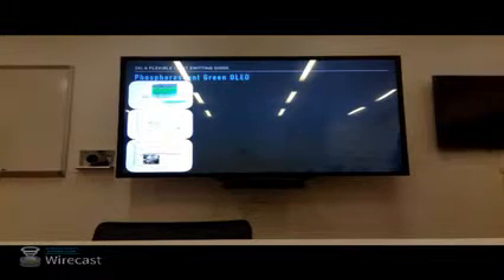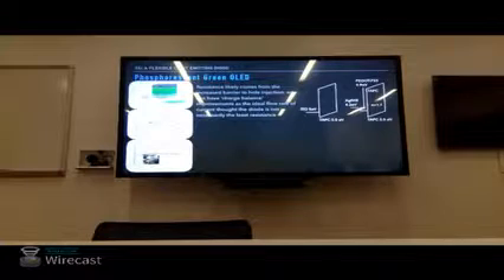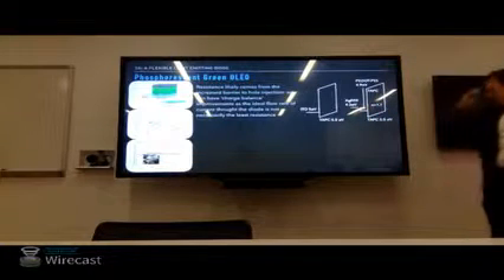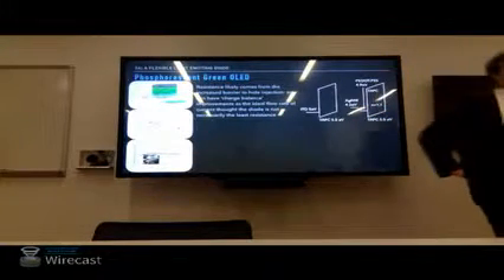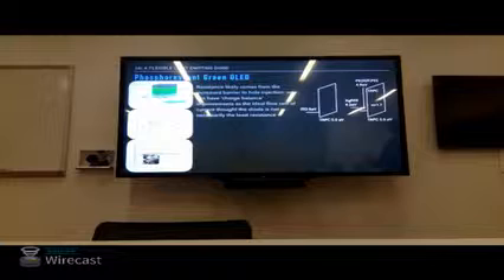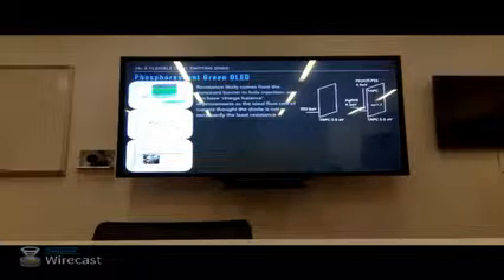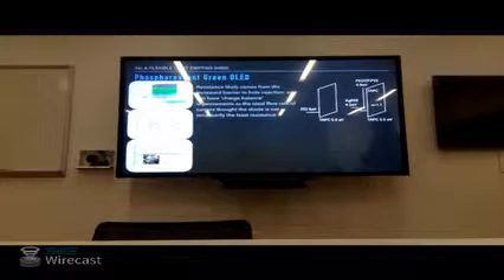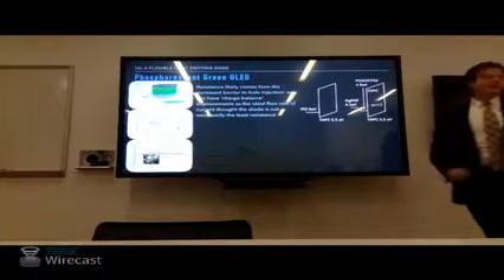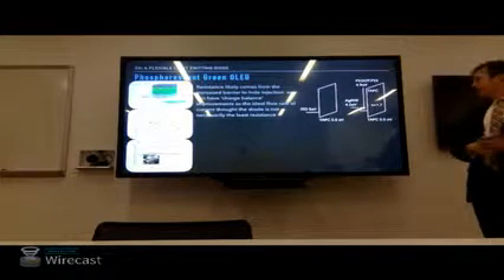So let's just take a minute to understand why we get a better device from a more resistive electrode. We have a work function difference now because we're not comparing silver to silver like in the solar cell, but we have ITO to silver. We have more of a barrier to hole injection here. So that's going to lead to that resistance. However, if we think about charge balance, which is restricting the charge flow to get more of an ideal rate to suppress loss mechanisms that could be there with a higher amount of positive charge carriers in our device, we could actually posit that perhaps the charge balance is better when using this energetic structure rather than ITO. The addition of the p-dot layer is going to add some series resistance as well.